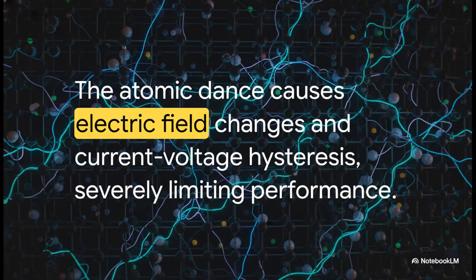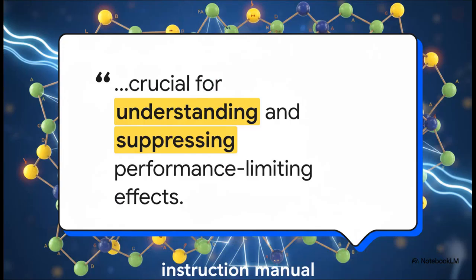So what does this microscopic atomic dance actually mean for us in the real world? Well, it causes local electric field changes that lead to something called anomalous current-voltage hysteresis. Basically, the solar cell performs differently depending on whether the voltage is going up or down. The ions migrating through the material create internal roadblocks for the electrons trying to get out. It creates major inefficiencies. The cell literally gets tired because its internal structure is migrating. This hysteresis is without a doubt one of the single biggest roadblocks limiting the long-term performance and commercial stability of perovskite solar cells today.